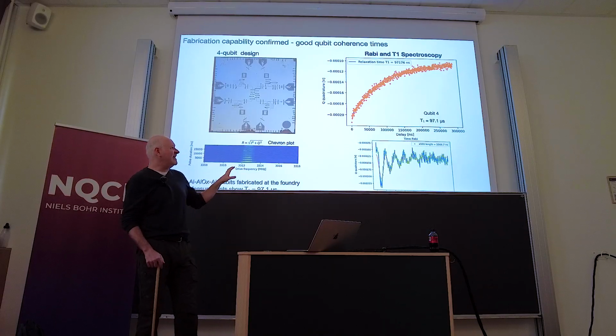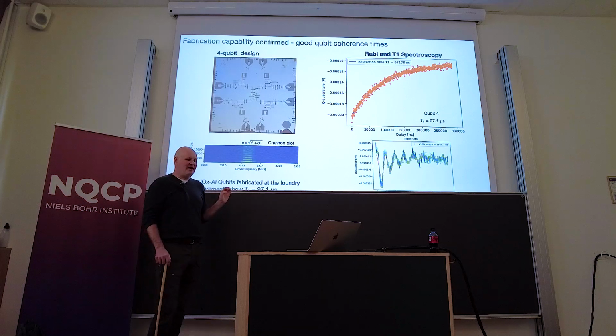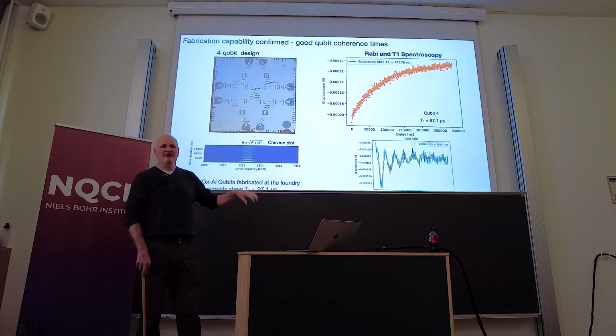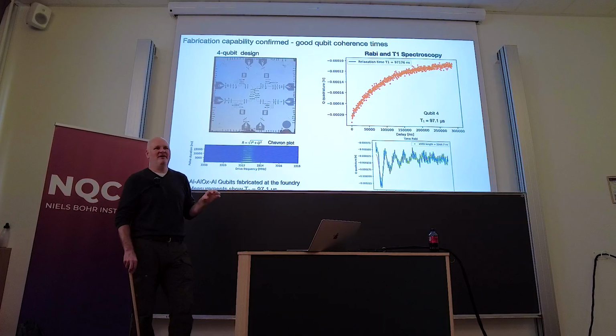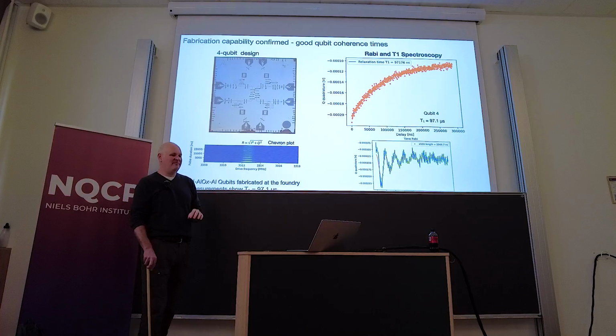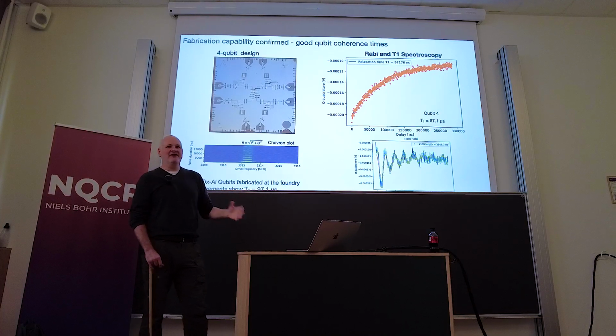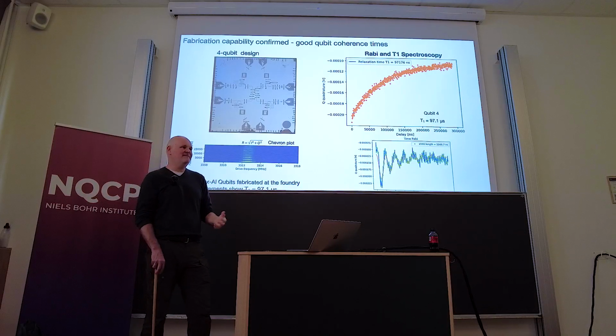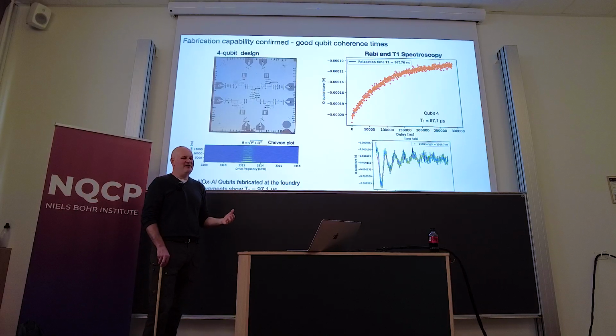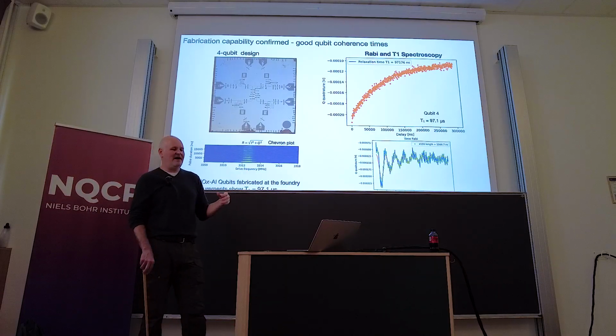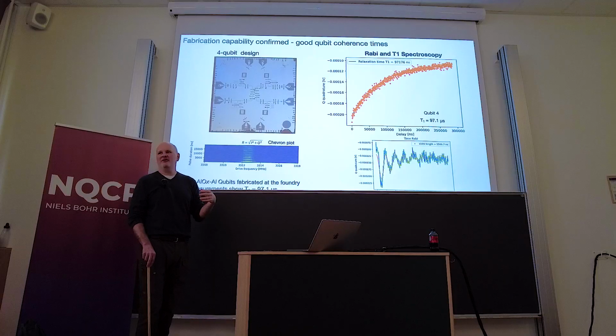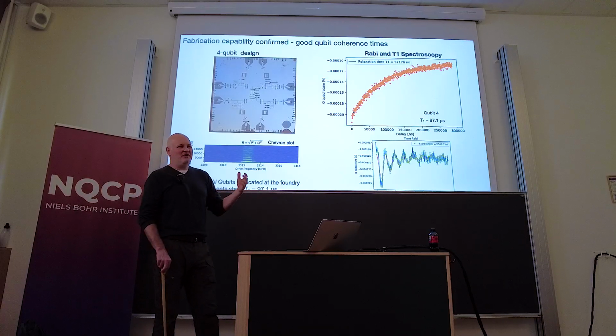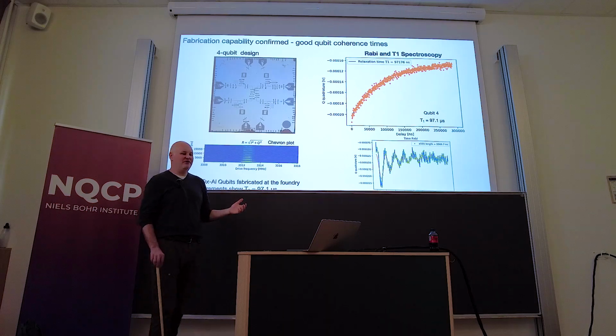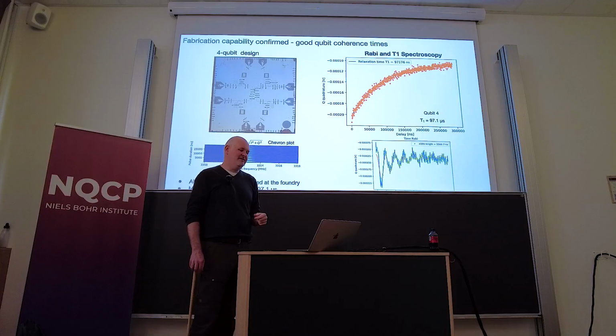The reason that we don't have a ton of data on a lot of samples is because we're completely fridge limited, in that we don't actually have a dilution fridge in the Molecular Foundry currently. So we have to beg, borrow, and steal time on other people's fridges on campus, in the physics division at LBL, and that makes it very slow. So the turnaround becomes incredibly tedious, because not only do you have to wait for scheduled time, but if it's not your fridge and someone else from that group has to do something quickly, you're the first person to get bumped. And so you can make as many devices as you want, but you may only be able to measure 1 chip in a month or in 2 months. And this really handicaps the whole process.